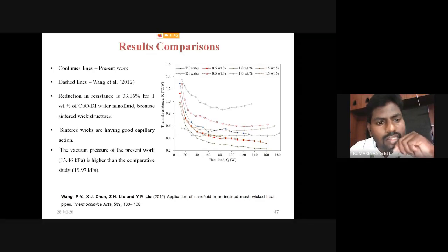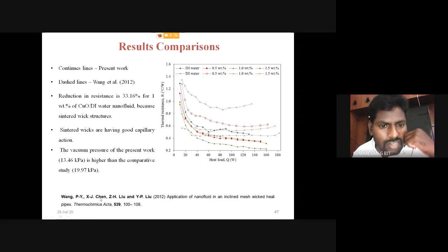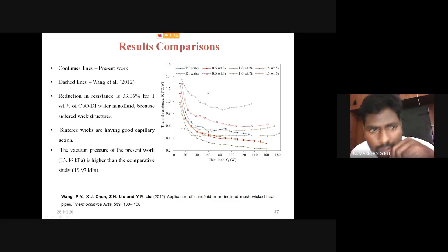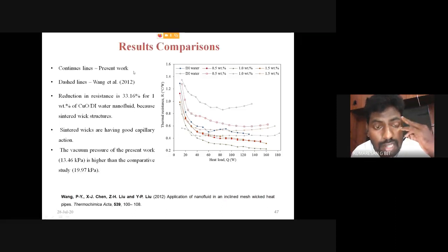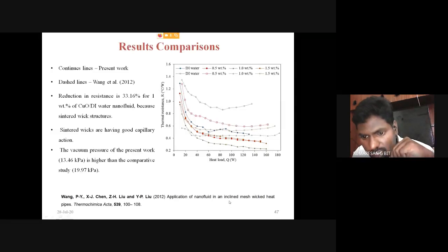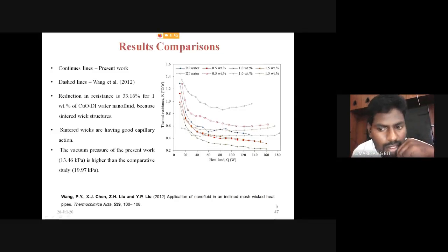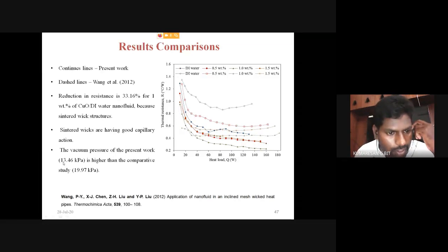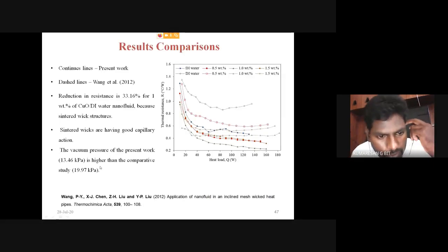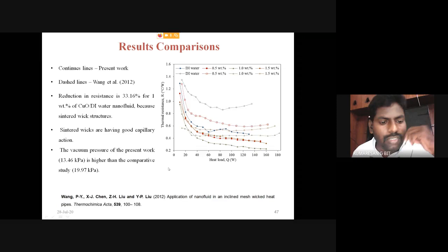and it is for the sintered structures. It also shows that sintered wicks have very good capillary action, because the continuous line, the present work, attained a very low thermal resistance value compared with that of Wang et al. Wang et al. used an inclined meshed heat pipe, whereas here I used the sintered heat pipe. That's why sintered heat pipes have very good capillary action because of their improved porosity and permeability values. The vacuum pressure of the present work is about 13.46 kilopascal, which is somewhat lower than that of the comparative study, 19.97 kilopascal.